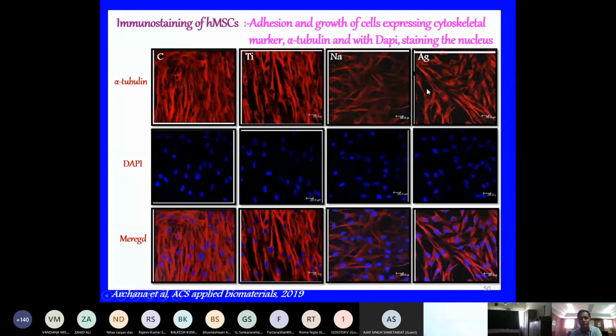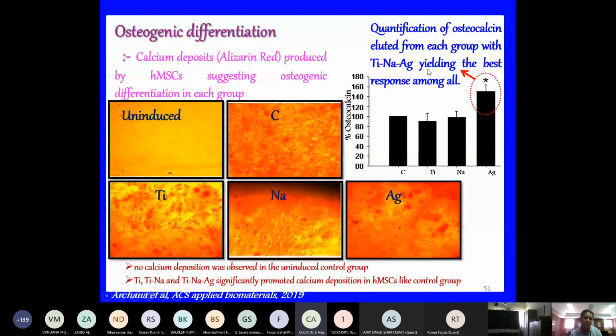So I want to say that although we modified the surface by different chemical or surface modification techniques, the silver containing samples are also non-toxic to these MSCs. So silver containing samples can be useful for biomedical, implant or medical device applications. And we also do a lot of studies on osteogenic differentiation. Osteogenic differentiation means calcium deposit formation by the MSCs. This suggests that the surface has osteogenic differentiation ability.